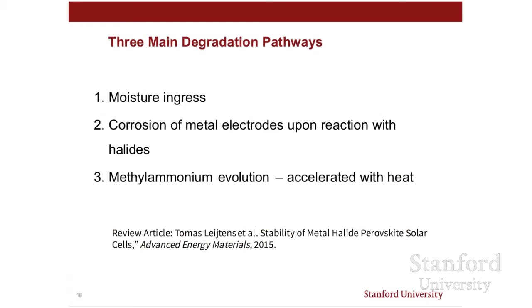So that's the good news. A balanced webinar has to present some of the bad news as well. These materials are very sensitive to water. A lot of you probably know that salts take up water, and these perovskites are no exception. But that just really means that the panels need to be packaged well. And it means that you need to cover the perovskite with an electrode promptly in the factory. You wouldn't want to have perovskite films sitting around, especially if the factory were in a humid environment. So you need to get it packaged promptly.